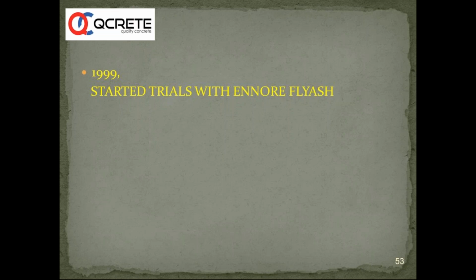They were continuously telling that the fly ashes in India are highly inconsistent, and we cannot produce good quality concrete with this. So my point was, with the inconsistency that is always there with this kind of fly ashes, we can make sufficiently adequate concrete which can meet all the requirements as per IS 456, all the requirements of customer. We can make tailor-made concretes using fly ash. This was our effort actually, and ultimately after about 1,500 to 1,800 trials, we could convince and started production of OPC plus fly ash mixes actually.